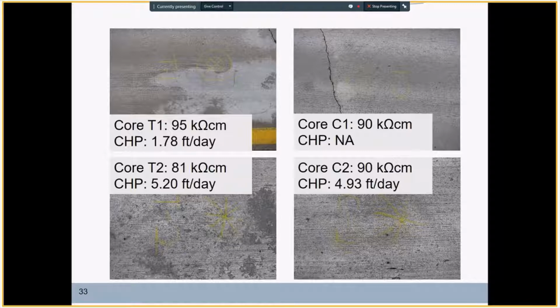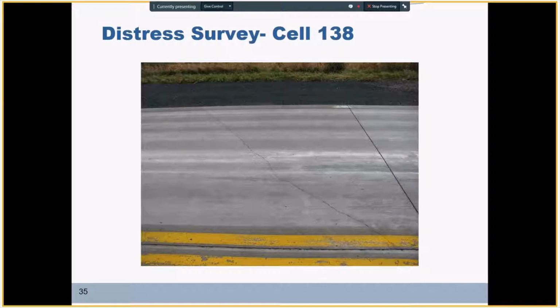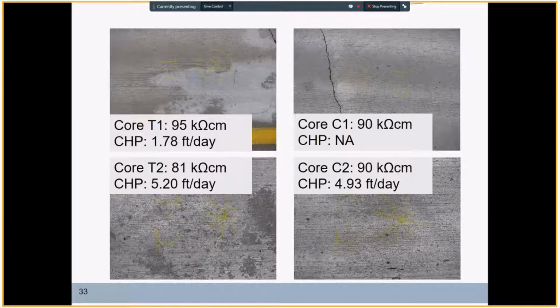These are the only cracks we have seen so far in cell 238 with 470 pounds. As I said earlier, we had some localized variation in concrete quality, a high concentration of mortar at the surface in this area. That may have been the main reason for crack initiation and propagation here, which I believe cannot be generalized to the rest of the pavement. The properties we saw here are not representative of the rest of the pavement, and we have not seen any other such cracks anywhere else in cell 238.